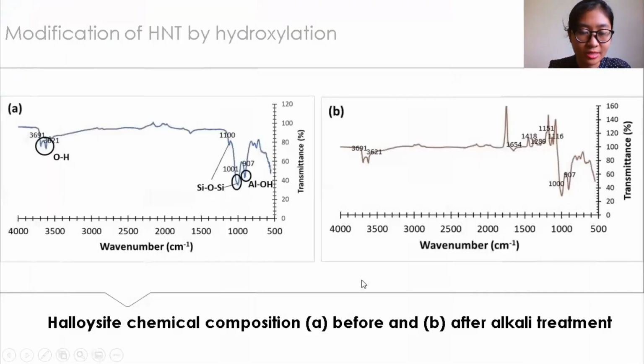First, we have here the absorbance spectra of halloysite before and after hydroxylation. There are 2 strong peaks here at these wave numbers. They can be attributed to the external surface consisting of a single bond stretching between silicon and oxygen molecules, and a bond stretch of the inner surface hydroxyl groups, also called aluminol groups.